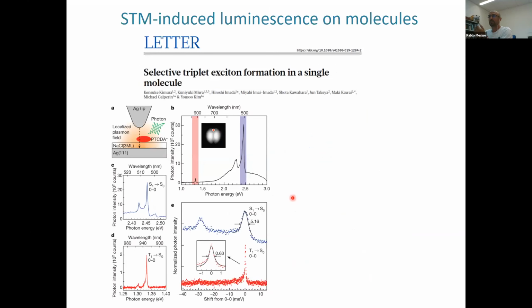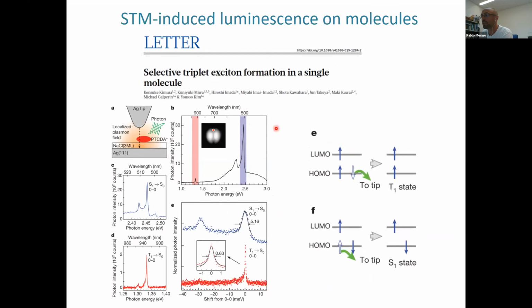And last year, we got another important paper in the field from the group of Yousoo Kim, and what they found is that for PTCDA, you could see electron hole pairs that decay not only from the singlet state, but also from the triplet state. So the singlet state is where you have anti-parallel spins, and the triplet state is where you have parallel spins. So let me go